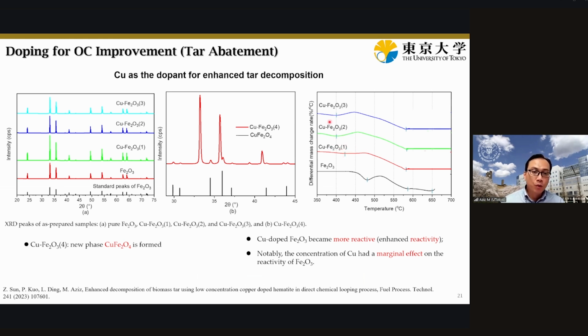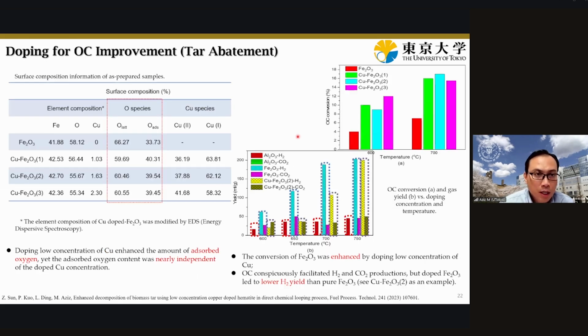But as we could see over the years, although we dope with a small amount, 1% of copper, we can get pretty excellent conversion rates compared to the original hematite, and also compared to the larger copper ratio. So we have also done simulations using DFT and experiments, and confirmed with XPS.